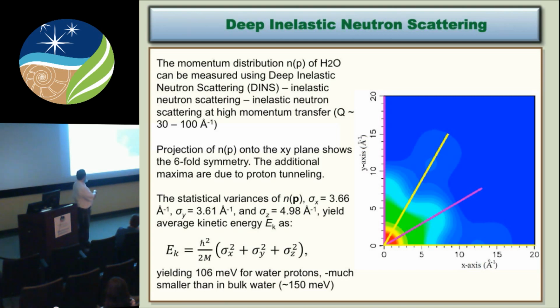There's another way we went then to try to prove this, which was to go to deep inelastic neutron scattering. In a deep inelastic system, you're looking at very high Q. So pretty much all you're looking at is the momentum distribution of the water molecules within the sample. Right? If there is tunneling going on, you can see here's the 6-fold orientation here. You would expect an extra peak between the two. You get vibrations as the water is moving between the 2 positions, and indeed the deep inelastic very clearly showed this extra peak within the sample.